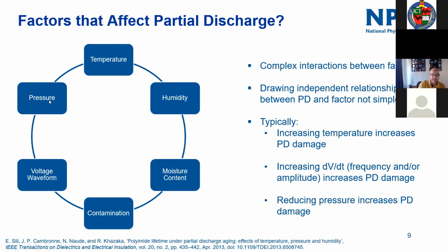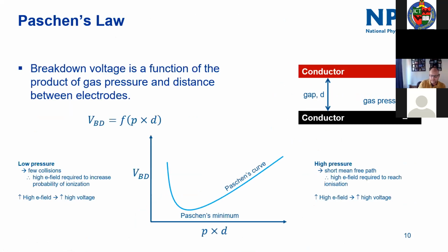Pressure I've already talked about, that could be an important aspect. We don't really understand the effects of temperature very well, particularly in the range of dielectrics we're likely to be dealing with within our industry. Humidity is always, again, and quite honestly, we don't understand which way humidity will affect. Obviously, organic materials will take up moisture depending on the humidity condition. They'll change their moisture content, but how that affects their PD performance is largely unknown. And then, of course, you've got the issue of contamination, and that may well be affecting surface insulation resistance by inducing electrochemical corrosion, which may in effect also change the PD response as well. Oh, I've done that one already, my apologies.